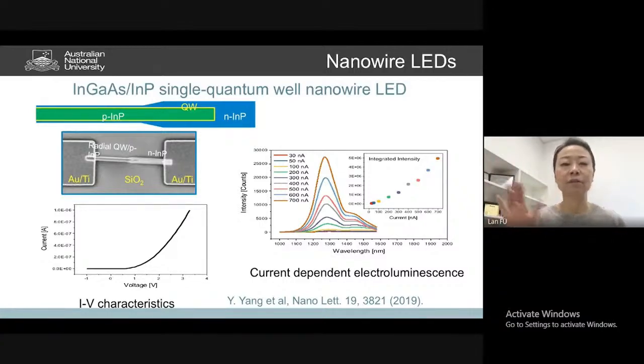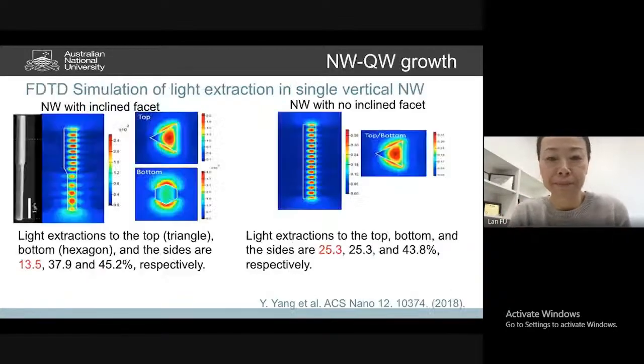the etched P-type core and N-type shell can be simultaneously contacted. So by doing that, we can inject current and measure this nice turn on of this diode, the IV characteristics. And if you look at the electroluminescence, by injecting current, we can see this enhanced luminescence as a function of the current injection, which really shows that we have got a good LED device coming from this tiny little nanowire, which is only a few micron in length and 300 nanometer in diameter.